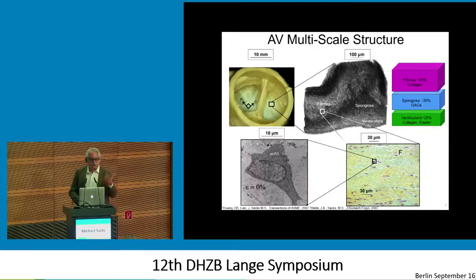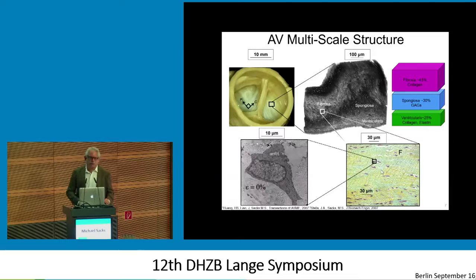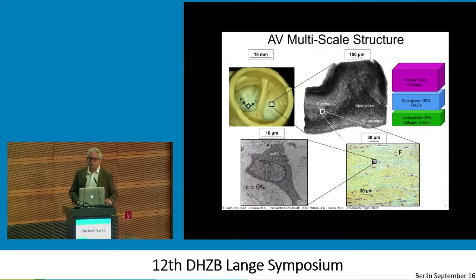These layers have very complex structures of dense fibrous collagen, glycosaminoglycans, and then a very interesting elastin-collagen-rich layer. And if you go further down, you'll see these are populated by — for dense connective tissue — a fairly large amount of what are called valve interstitial cells. These cells are very, very synthetic. Compared to other tissues like cartilage or tendon, they have about a 10% volume fraction, which is about three to five times that of these other tissues.